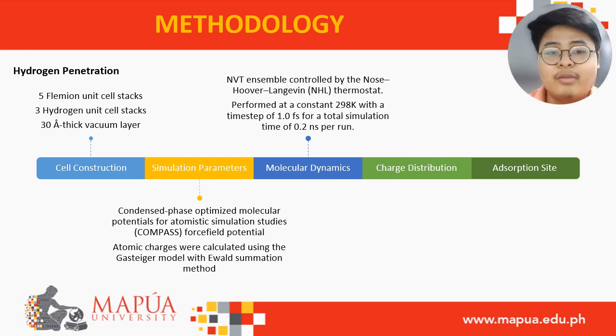For the molecular dynamics, we made use of a constant temperature molecular dynamics, with the Nosé-Hoover Langevin thermostat, performed at a constant 298 Kelvin with a time step of 1 femtosecond for a total simulation time of 0.2 nanoseconds per run.